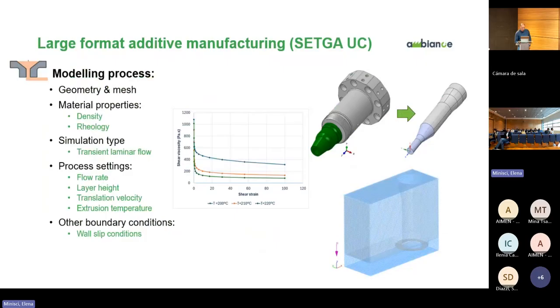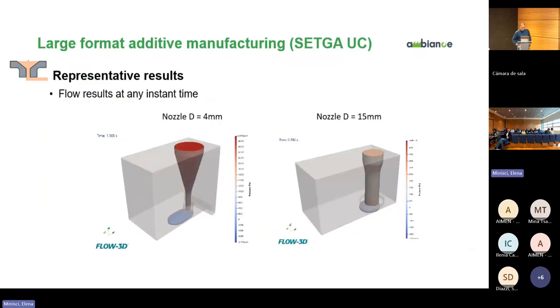And here, the boundary conditions of the process are the flow rate, the layer height, translation velocity of the nozzle, and also extrusion temperature. Here we have a couple of simulations, animation of this type of simulation for two different diameters of the nozzle. We can see more or less in detail what is the process and what I mentioned before about the free surface. So we have a translating nozzle in this case, and the top of the filament is free in contact with air. So this needs a special boundary condition.